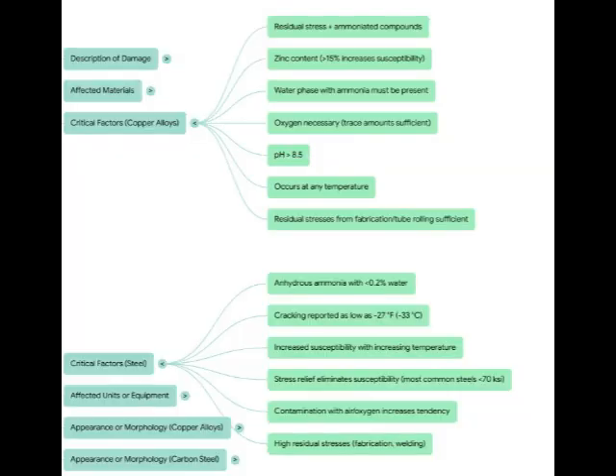Okay, let's focus on those copper alloys first. Brasses. We see them a lot in things like heat exchanger tubes. What's the specific recipe for disaster there? It sounds like it needs a perfect storm. It really does. For brasses, like Admiralty brass or aluminum brass, the material itself is the starting point. The sources are clear. Susceptibility really jumps up once the zinc content gets over 15%. 15% zinc, that's a specific number. It is a key threshold. But just having high zinc isn't enough. You need those environmental triggers too, and they're quite strict.